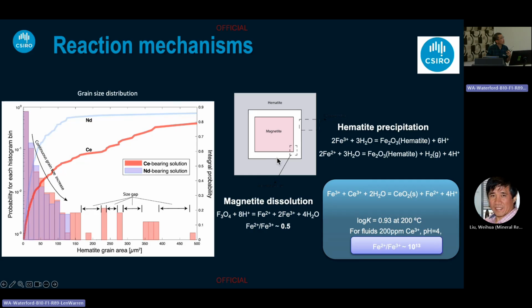So the results show that having cerium 3 in the water really changes the way you react at the grain surface, when dissolution of minerals and precipitation of new minerals happen. The reaction shown here is as follows. You have magnetite dissolution first: magnetite in acidic water dissolves iron 2 plus and iron 3 plus into the water, giving a theoretical ratio of the two of 0.5. And this is how you precipitate hematite at the surface as well: you have iron, water and hematite, with acidity, and then you have this reaction as well.